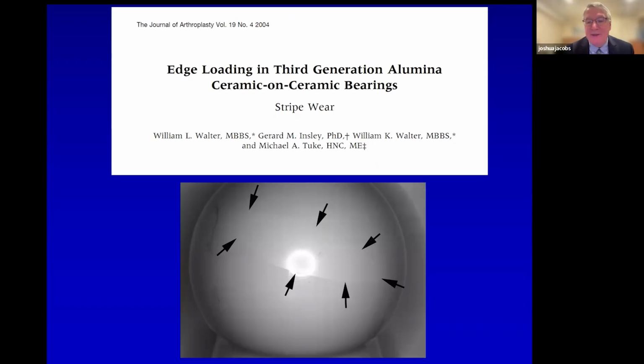And just to take a step back, the typical bearing surfaces that we use currently and historically have been a hard-on-soft bearing, meaning some kind of hard material such as a metal or ceramic on the femoral side, and on the acetabular side, it would be a polymeric material. And where we are currently is the polymer that we use is a highly cross-linked, ultra-high molecular weight polyethylene component. We got there through trial and error through many decades. And this system of hard on soft is currently the standard of care and behaves very well. However, we've looked at hard on hard systems for a variety of reasons, some of which I'll cover shortly.